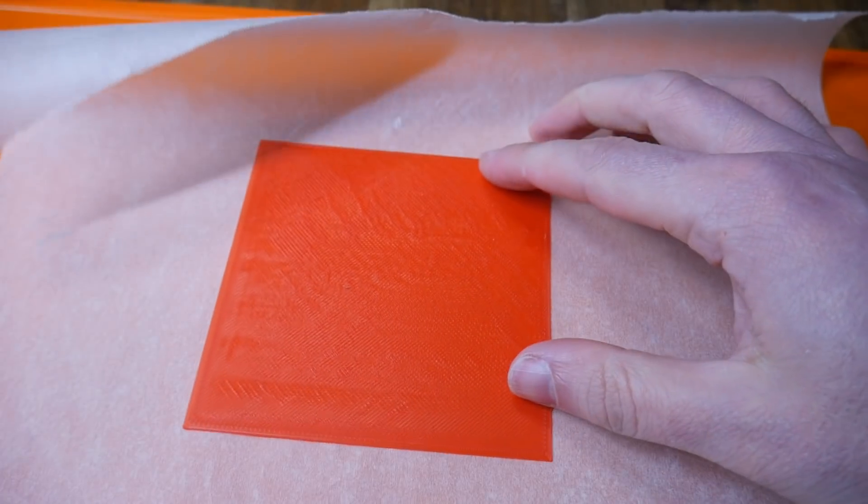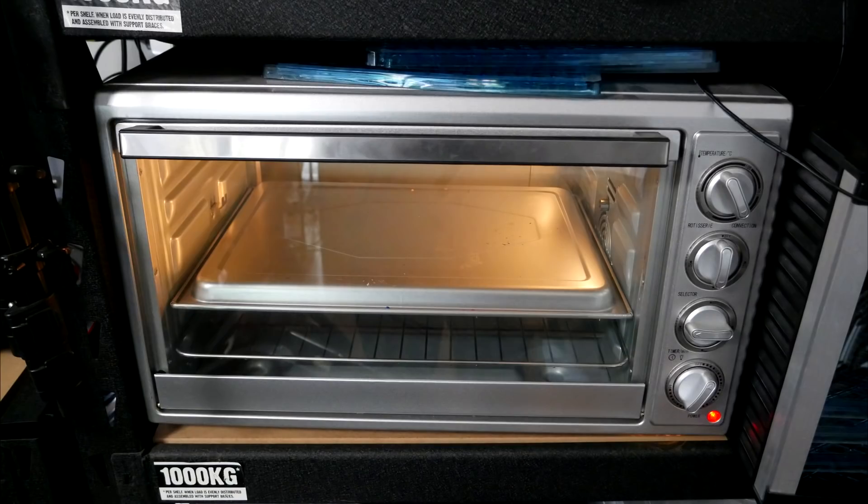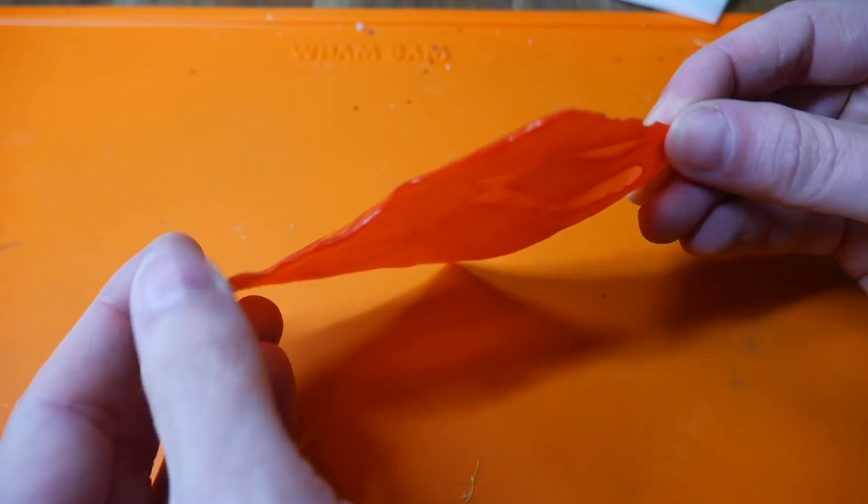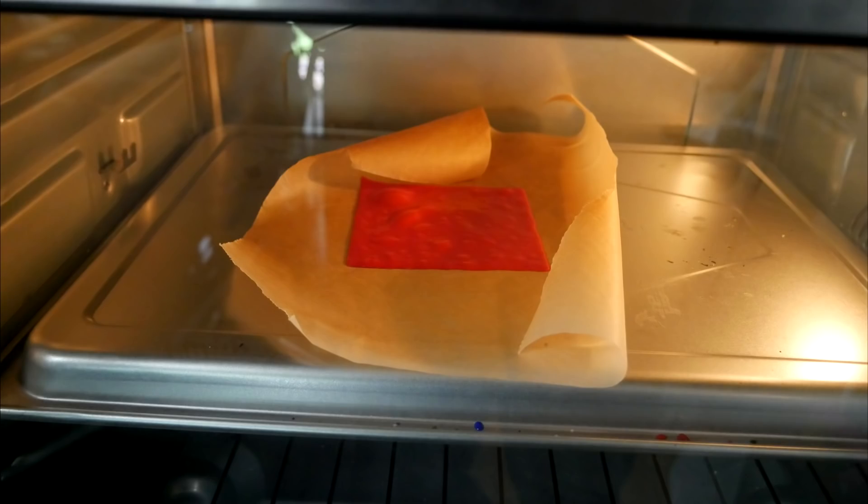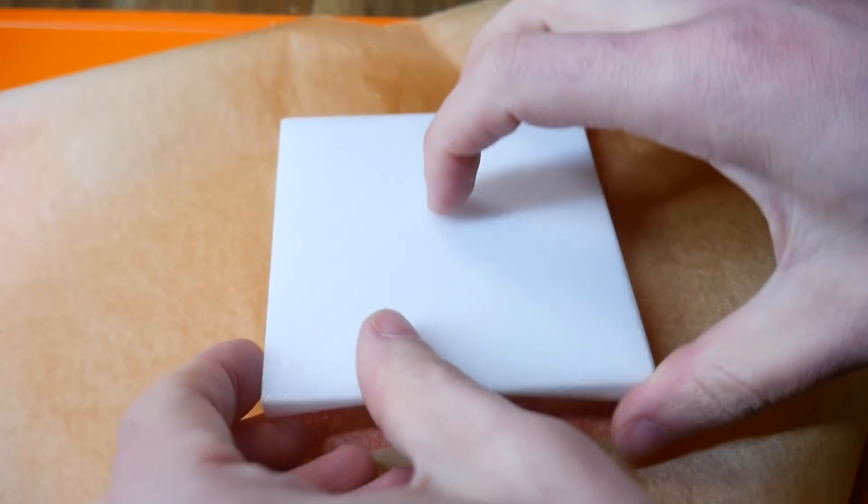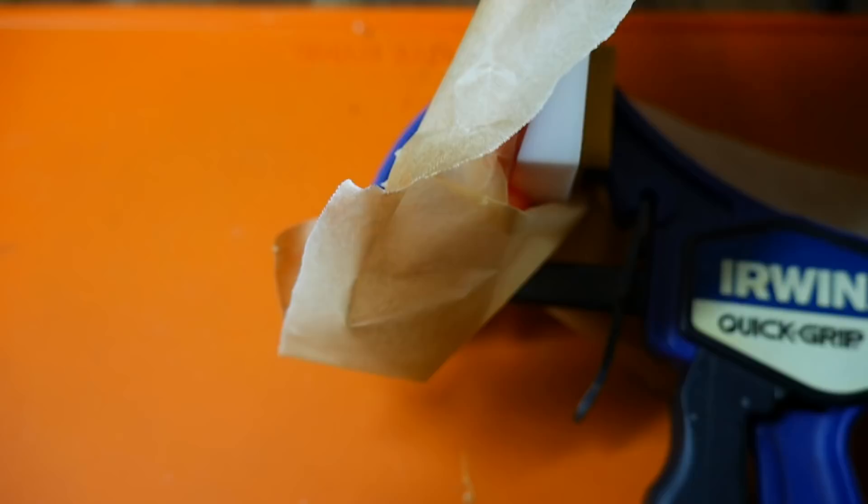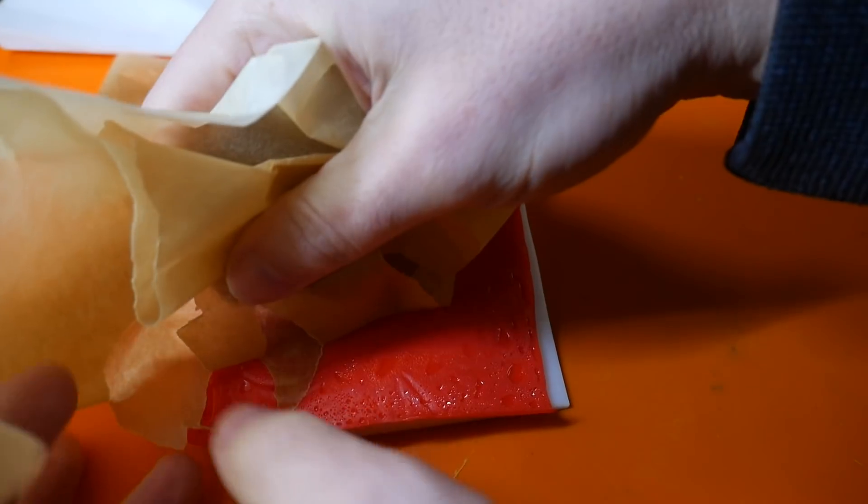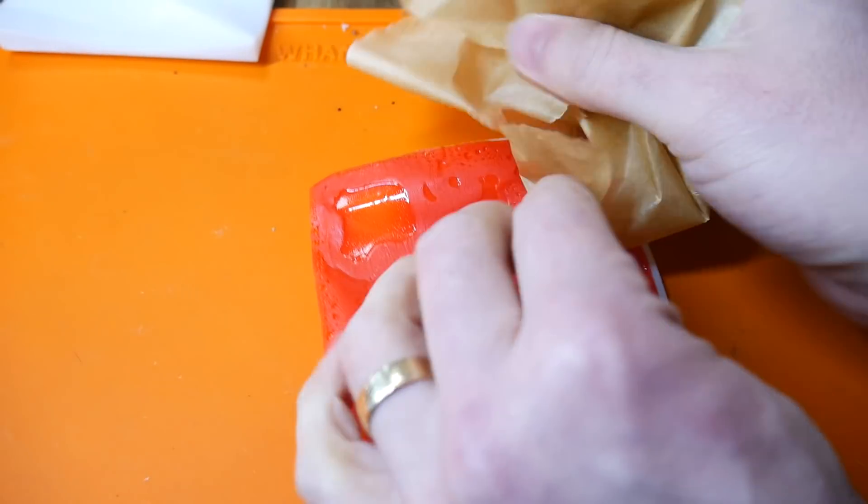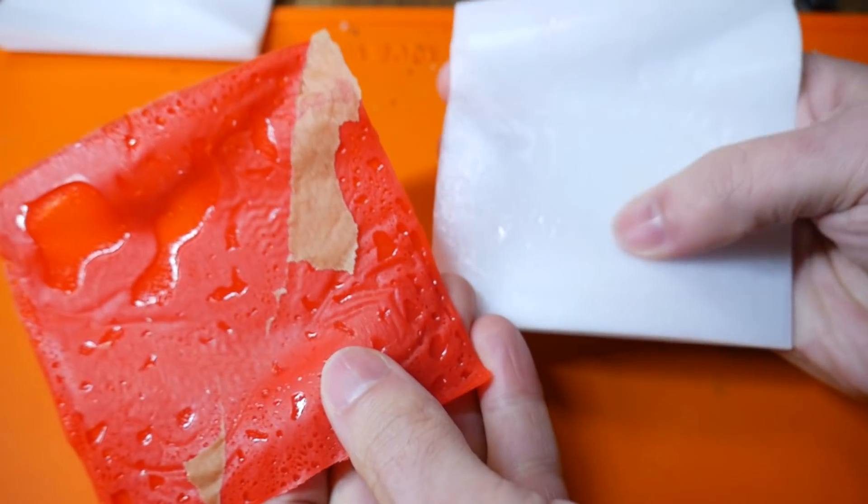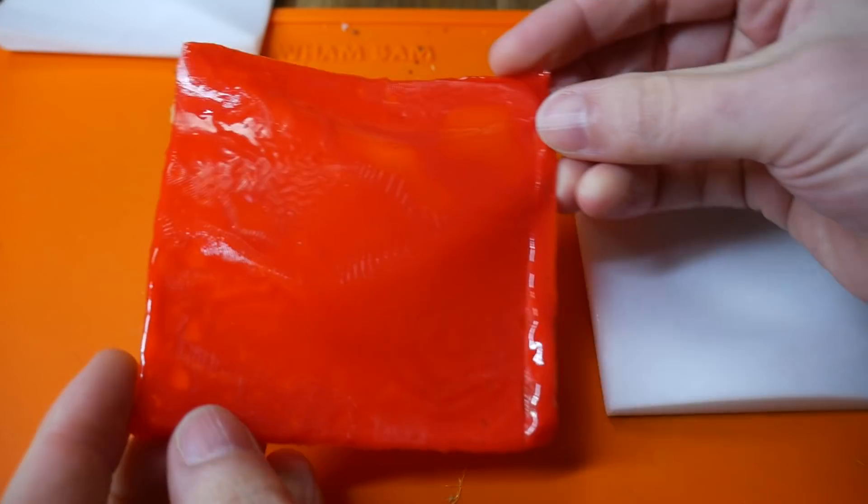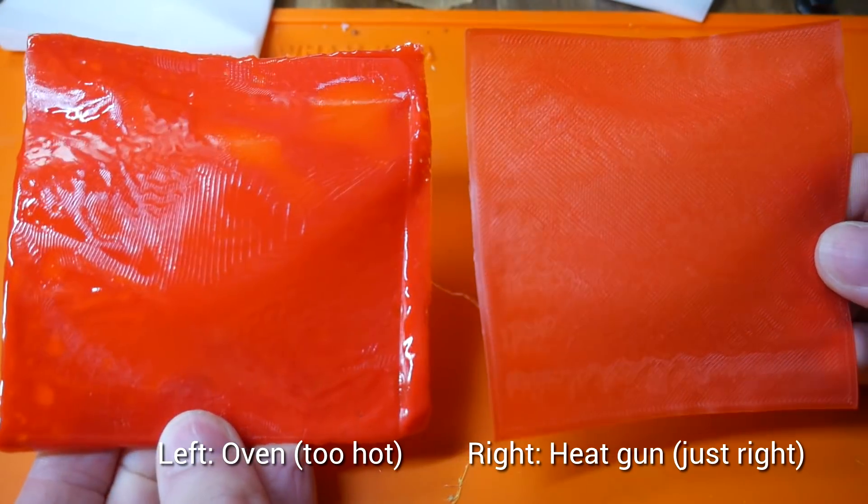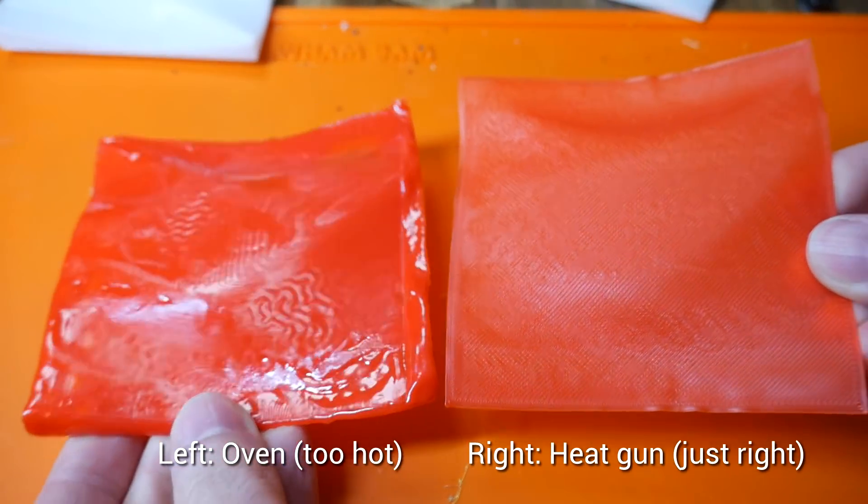I also wanted to experiment with using an oven to heat the blank, setting it on regular baking paper. I have a cheap standalone oven for the purpose of melting plastics, and I wouldn't necessarily recommend using your normal kitchen oven. It's actually very easy to overheat the plastic, in which case it shrivels and deforms in shape. This one was a little closer to the ideal temperature but still too hot. Leaving the plastic on the paper and inserting it with the plastic into the mold made it easier to work with, but it also blocked visibility for correctly aligning the two halves of the mold. Again I used multiple clamps to hold the two halves together while everything cooled. As I mentioned, I let the plastic get too hot, and that means it stuck to the paper. The PLA did separate nicely from the PETG, but the high temperature actually changed the surface of the mold, and this means the finished product was soft enough to take on this distortion as well as the layer lines. Because of this, for thin materials I'd highly recommend sticking with the heat gun. The results are much, much better.